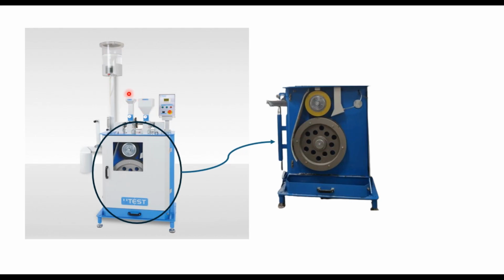Now here is another arrangement for feeding of emery powder. So in the second part of the test, we feed this emery powder and water. It is fed through this mechanism here. So emery powder and water, or the silicon carbide grit and water, are fed at this point of contact here so that it abrades the surface of the sample.